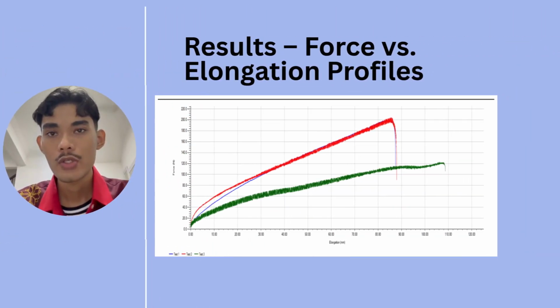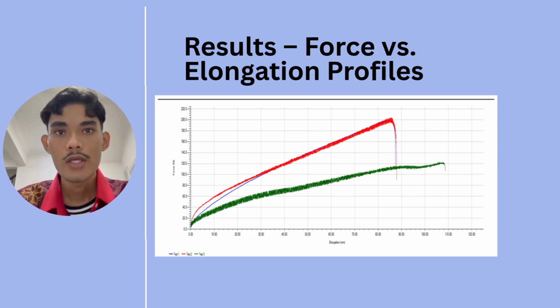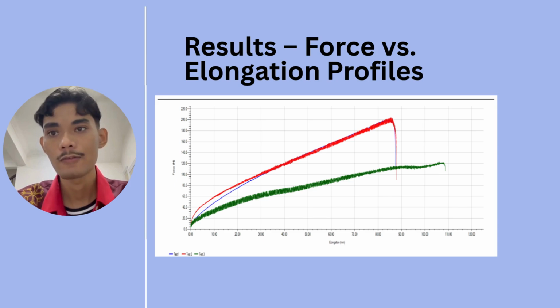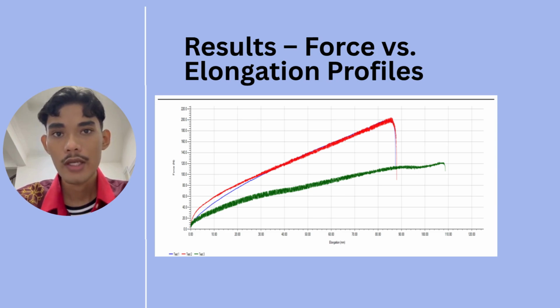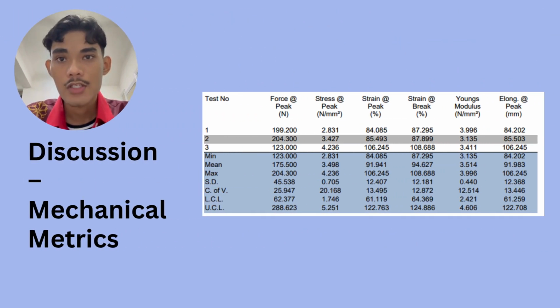Let's take a look at the graph showing force versus elongation, which simply measures how hard we pull versus how far the material stretches. Looking at the lines, we can see two very different behaviors. Test 1 and Test 2, shown by the red and blue lines, followed almost the exact same path. They were able to hold a much higher force but broke earlier, around 87 millimeters. On the other hand, Test 3, shown by the green line, behaved differently. It could not hold as much force, but it stretched much further, reaching over 108 millimeters before breaking. This tells us right away that different parts of the material do not behave exactly the same way. Let's dive into the specific numbers to understand this better.